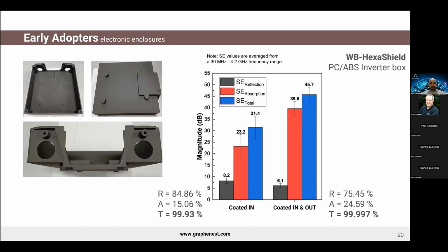The water-based HexaShield was tested in a real-world application. In this case, we made some tests with electronic enclosures. We took a polycarbonate ABS inverter box from an electrical vehicle, an automotive inverter, as can be seen in the image at the left of the slide. And we tested two different scenarios to measure the shielding performance using the equipment that you saw on the previous slides. We spray coated the box only inside, and we also spray coated the box inside and outside. In both cases, the coatings are roughly 30 to 40 micrometers thick.